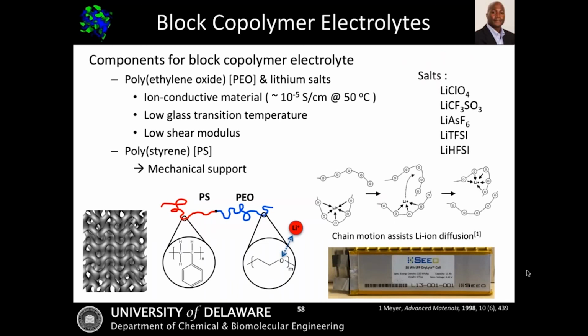So in this particular case, we're going to start out talking a little bit about the archetypal system, which is basically polystyrene polyethylene oxide. And one of the reasons for that is as follows. Again, what I want is an electrolyte material that's able to conduct ions. In this case, polyethylene oxide is a very good material for that. It's got a reasonable ion conductivity and a low glass transition temperature, which helps facilitate ion motion. One of the difficulties with this material, though, is that it has a relatively low shear modulus, so it's not really the most mechanically stable material.